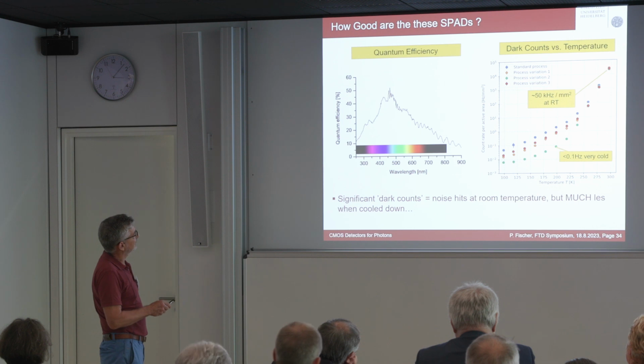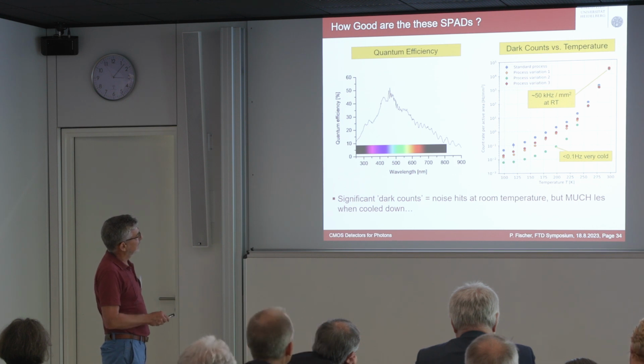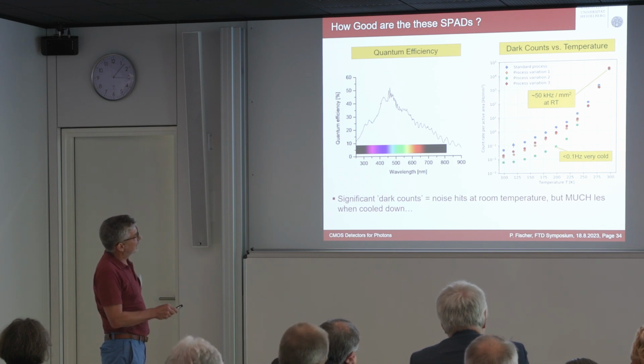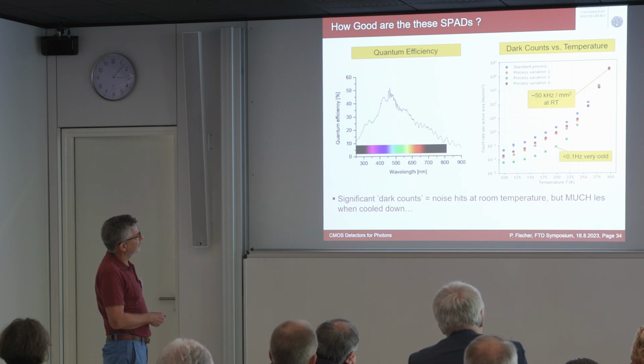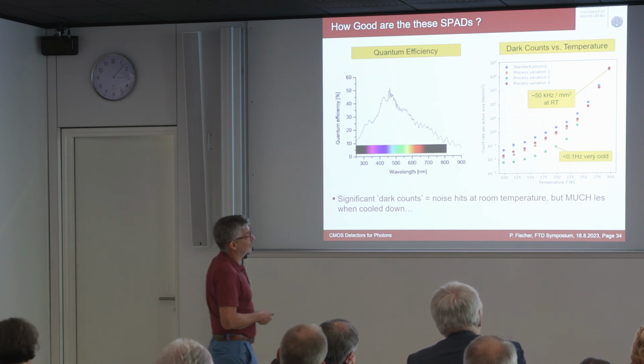So here are the dark counts in area as a function of temperature. And at room temperature, we have 50,000 discharges per square millimeter. That is a lot, and that is the same for commercial devices. For SiPMs from Hamamatsu it is roughly the same number. So 50,000 per square millimeter is a lot. So it's hard to see the moonlight with this at room temperature.